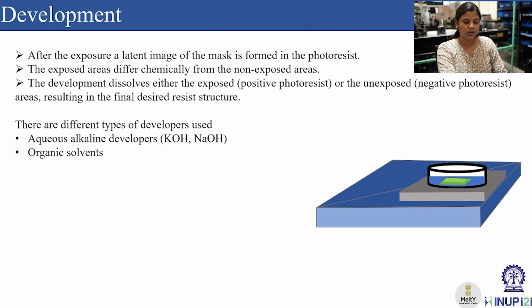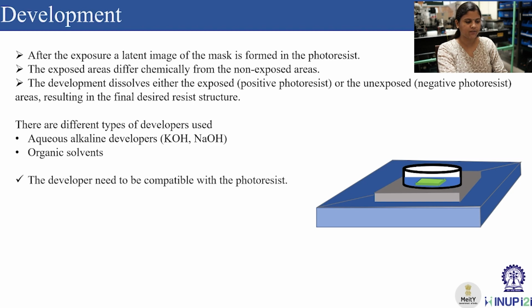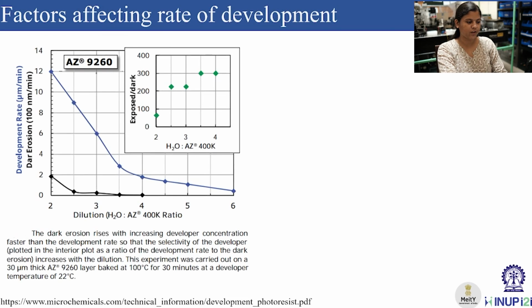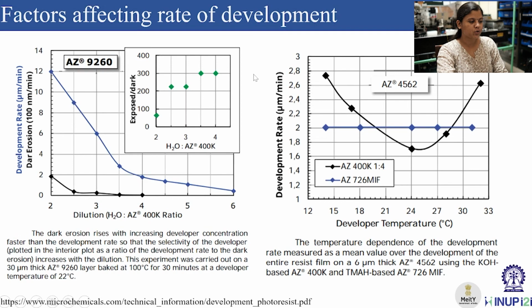Here this animation shows how the development is done. In a petri dish, we put the developer and we put the exposed structure in that, and then it is shaken for some time, and after that we get the final structure. Now, one important thing to keep in mind while choosing the developer is that the developer needs to be compatible with the photoresist, and an optimum degree of dilution and temperature need to be chosen for better development. We will see how factors like dilution and temperature are affecting it. In this figure, we dilute the developer with DI water in a certain ratio. As this ratio is changing, that means as the dilution is changing, we can see that the development rate is also decreasing.